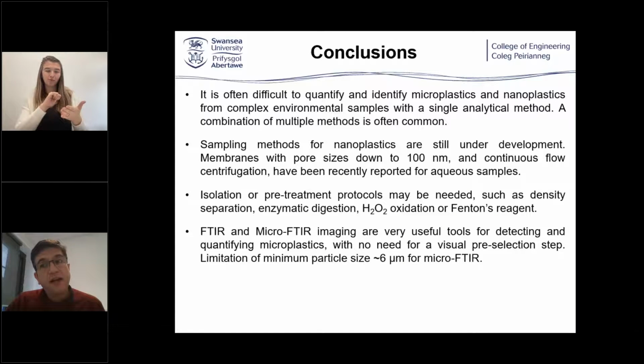FTIR and micro-FTIR are some of the most common tools for the detection and quantification of microplastics. You don't need a visual pre-selection, particularly when using micro-FTIR, but you have a limitation on the minimum particle size, about 6 micrometers for micro-FTIR.